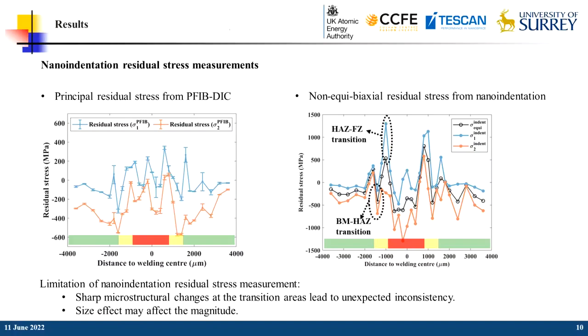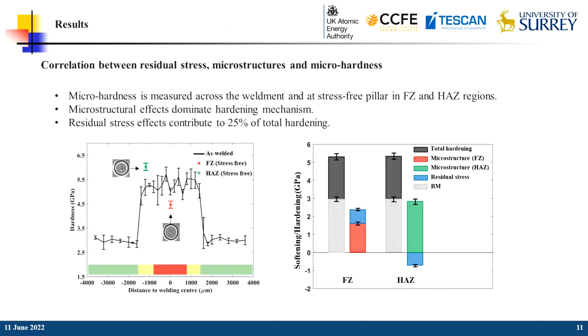The sharp microstructure and residual stress gradients usually exist in these transition regions, which indicates that a location-dependent stress-free reference at a high resolution is desirable to improve the quality of the nano-indentation residual stress measurements. We also evaluate the local hardness, and the local hardness values depend on the residual stress and the microstructure, for example, the grain size, the precipitate size, etc. Our nano-indentation methods enable the quantitative evaluation of the microstructure and the residual stress effect on the hardness.